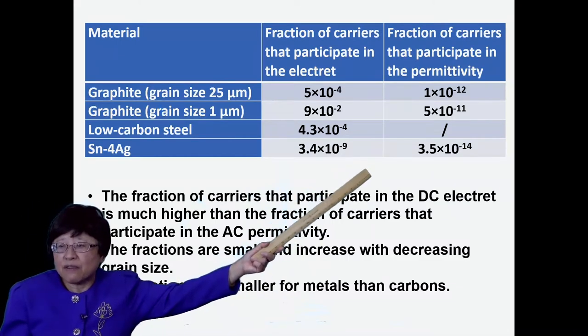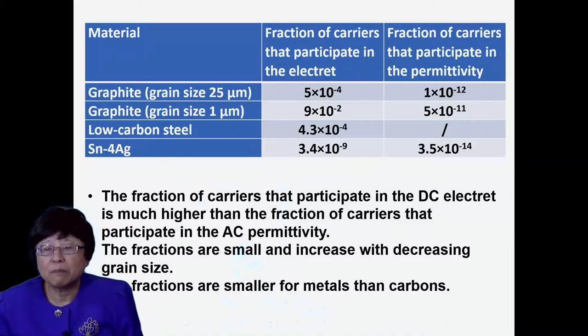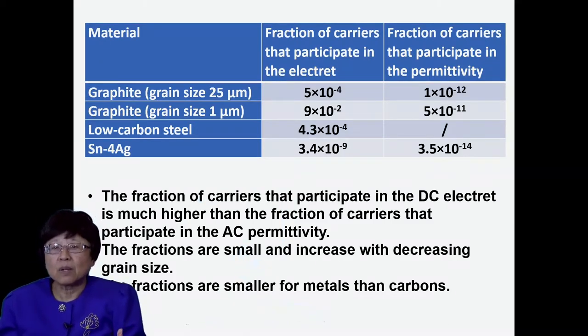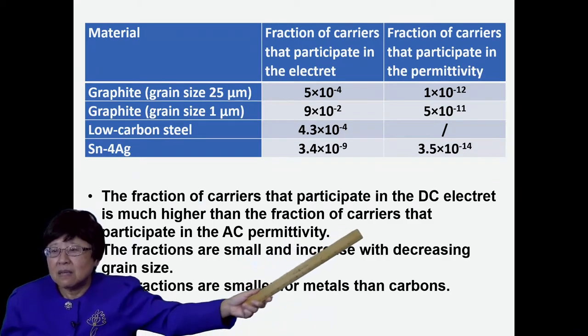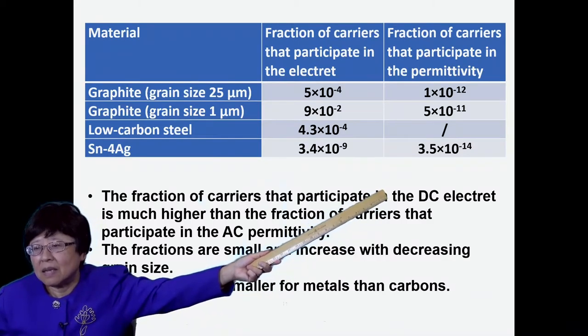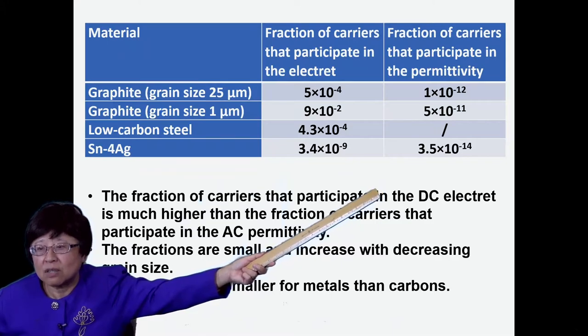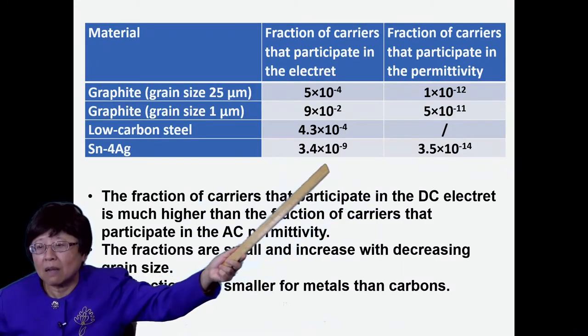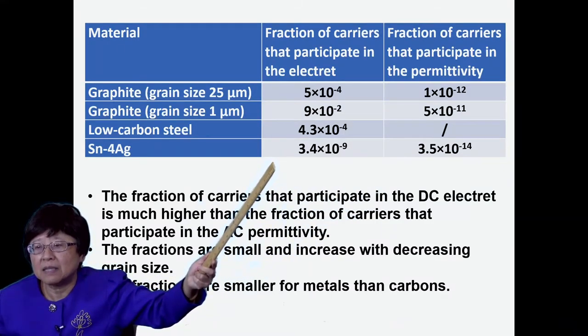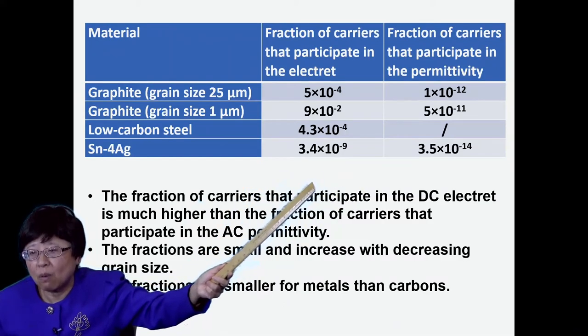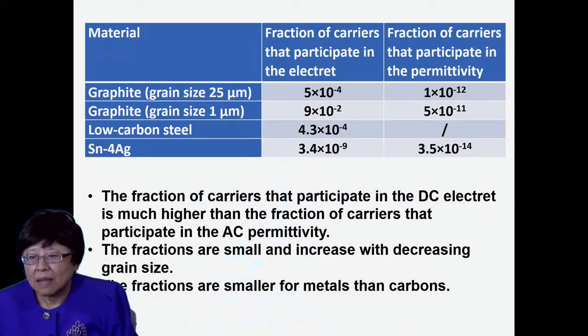Also shown here is the fraction of carriers that participate in the permittivity, that is in the AC polarization, as indicated by the capacitance measurement. It's also a very small fraction, and that fraction is smaller than the fraction of carriers that participate in the electret by quite a few orders of magnitude. Okay.